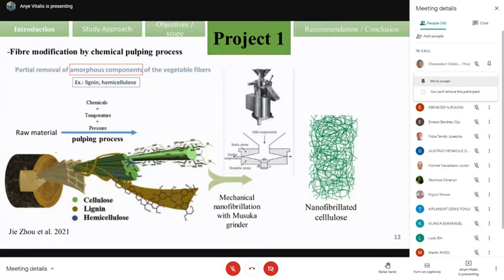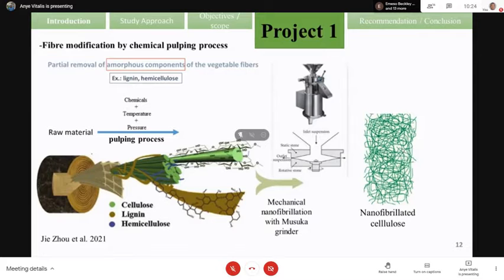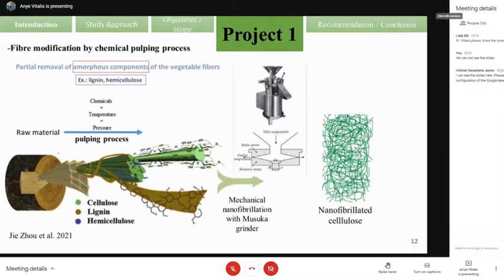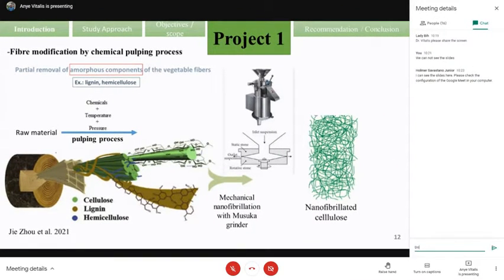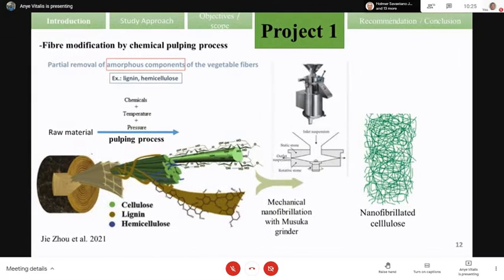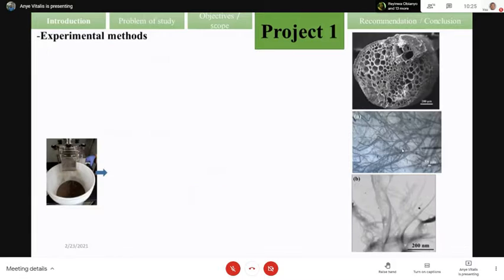Now the cellulose that will be obtained, which is in micro size, has to go through the Masuko grinder for nanofibrillation. With the shear stress that we apply to our fiber using many cycles of nanofibrillation, we can have nanofibers with a high aspect ratio, high specific area, high stiffness, and also good reinforcement efficiency compared to the whole fiber.